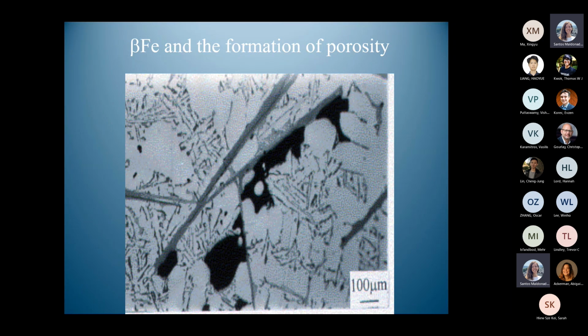So suck it away like this, but there are dendrites here. And so this bifilm will start wrapping itself around dendrites. And that's what's happening here. It's being pulled away here and pulled into the dendrite mesh. So the bifilm is clearly a very good initiation point for porosity in castings.